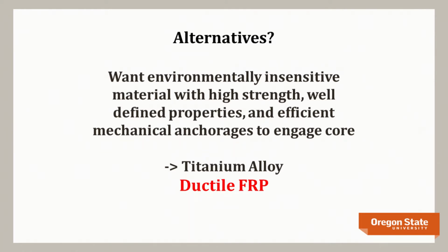And really what we want is something that's environmentally insensitive material with high strength but well-defined material properties. We'd like it to have ductility. And we'd like to have something that has inherent anchorage built into it. So we're not just relying on the bond along the length, but we can actually anchor the ends of them. And that's what leads us to titanium alloy bars. And really you can think of it as ductile FRP.